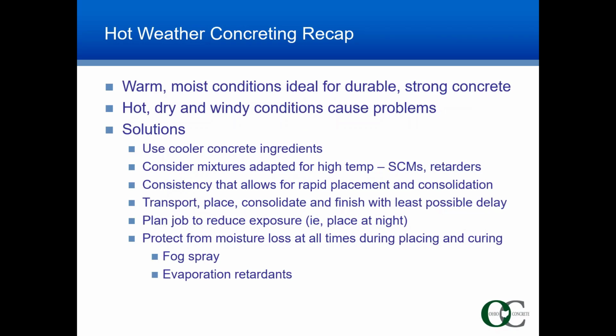So let's recap some of the items that we've covered on hot weather concreting. Warm, moist conditions are actually ideal for durable, strong concrete. So we want to enhance and create hydration of the cement. However, when we get into conditions of hot, dry, windy conditions, they can create problems. And as we've detailed, some of the solutions include cooling the ingredients that make up the mix, using mixes that have been adapted for high temperatures. Those include using supplementary cementitious materials such as fly ash or slag cement, or using retarders, liquid retarders.